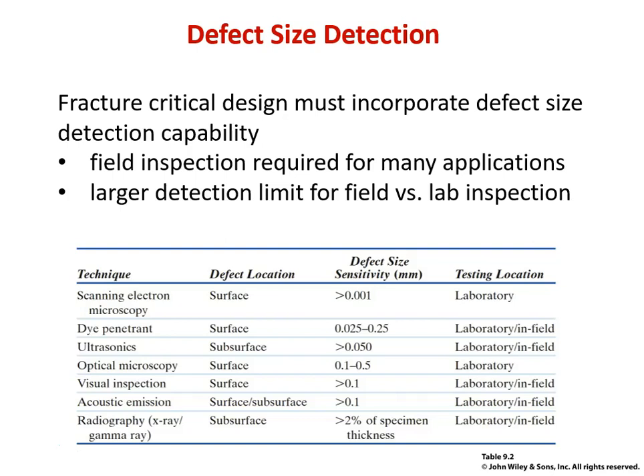Dye penetrant, which is a very easy in the field technique, you've got in the hundredths of millimeters. Of course, this is only capable of detecting surface flaws. Ultrasonic, about double the detection limit on the average, but it's much better for subsurface defects. Optical, good for surface defects again, very usable in the field, a tenth to half a millimeter. Very, very good visual, can get you to within a tenth of a millimeter. You know, that's obviously kind of part and parcel with optical microscopy. Acoustic emission, more laboratory based, not much better actually.